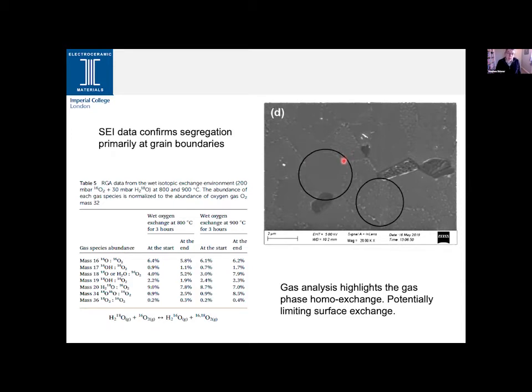But as well as doing the XPS and the SEI imaging, we also did some analyses of the gas atmosphere in the exchange. And in that case, we now see that there are some significant changes between the atmosphere at the start and at the end of the exchange, which is highlighting that there is indeed homo-exchange in the gas phase, and that that is potentially a further complication and limitation to the surface exchange coefficient.